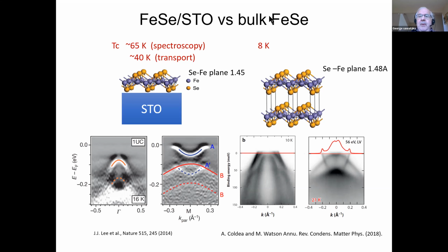Okay, let me take this out of the way here. So you all know what the structure of iron selenide is. It's not polar, which is very nice because many of the other materials, as you know, are polar, and that always creates a bit of a problem for surfaces. So for photo emission, it's very, very nice to have a non-polar material. Now, of course, when you put it on strontium titanate, it may be polar. As a matter of fact, it probably is. But let's just go ahead with this first.